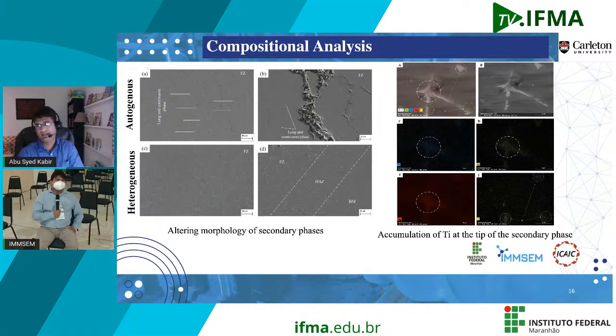So if we look at the scanning electron microscope images for the fusion zone in autogenous and heterogeneous, the basic difference between those two fusion zone structures is these long and continuous phases that are present in autogenous welds. We don't really see that kind of long and continuous phases in heterogeneous welds. That means we have titanium carbide nanoparticle in there. So it is understandable, it is kind of guessed, that somehow the titanium carbide nanoparticle prevented the formation of that long and continuous phase precipitates. Those are the harmful precipitates for the structure.